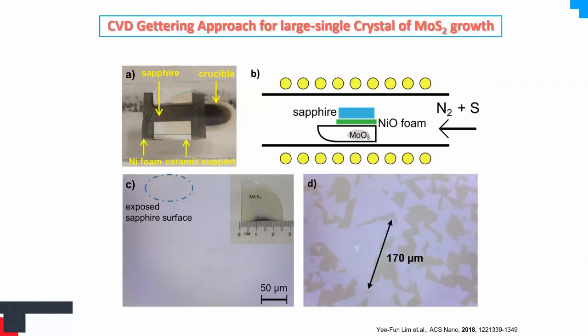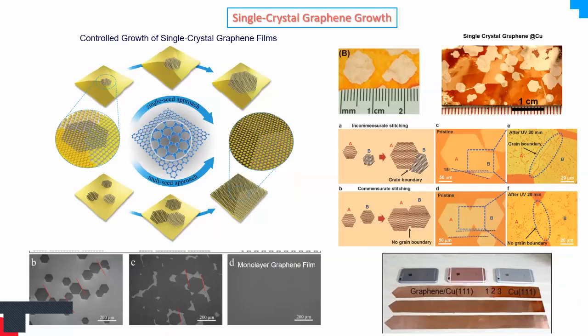Then some people also followed it, using this gettering method to grow other 2D materials like MoS2. This is one group from NUS. They started growing large single crystals of MoS2 using a similar method. That was if you want to control the nuclei to a single nucleus. Otherwise, there are also other techniques to grow single crystal graphene by controlling the orientation of the crystals.